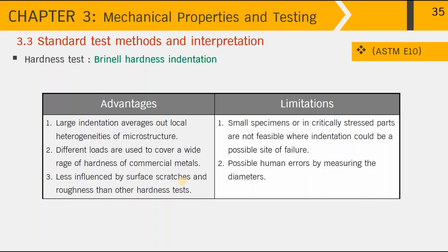Before doing the test, we have to cut the metal piece and grind the surface to make it flat and smoother. With the Brinell hardness test, we can prepare the metal surface with grinding alone. It's not necessary to go for a polishing step, and this saves a lot of time in preparing the sample. Let's hear some limitations. Since the indenter is large, it's not suitable for small specimens or for tests at critically stressed parts, because it may not be feasible where the indentation can cause failure.